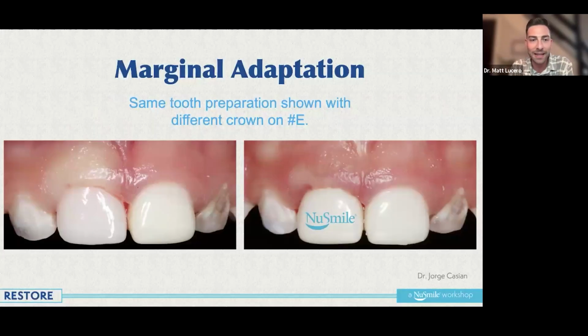Here's an example of that. This is the same tooth with two different manufacturers' crowns. You can see on the left, you get a little bit more blanching with that more flared cervical third of the crown, whereas the NuSmile drops into the sulcus and you don't have that same type of blanching going on. Now, blanching isn't a terrible thing, right? Because all of our stainless steel crowns, for the most part, cause a little bit of blanching. But if we're trying to mimic what's naturally there, a more gradual and a more biologic emergence profile is usually best, at least in my opinion.